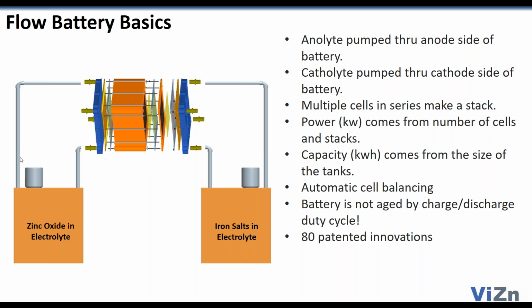We have targeted our system to be in the sweet spot of the utility space, which is this 2 to 4 hour ratio of power in kilowatts to capacity in kilowatt hours. Key thing in flow battery stacks in any large battery array is cell balancing. Our system has built-in electronic controls which rebalance cells to each other in real time while the system's running, and that minimizes the maintenance and also maximizes the stability of the capacity of the system, and you do not see the degrading that occurs in systems because of cell-to-cell imbalance.